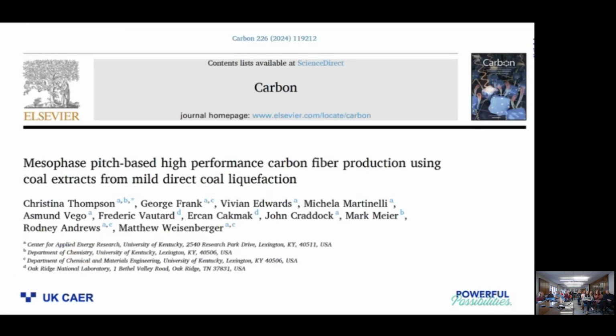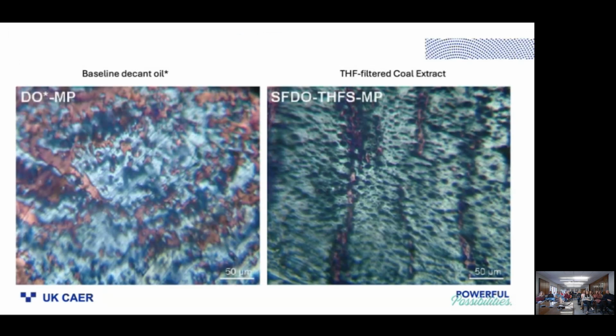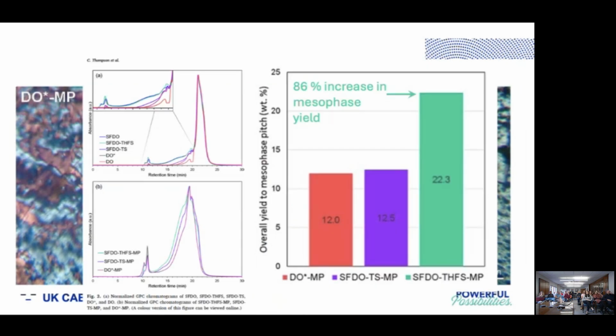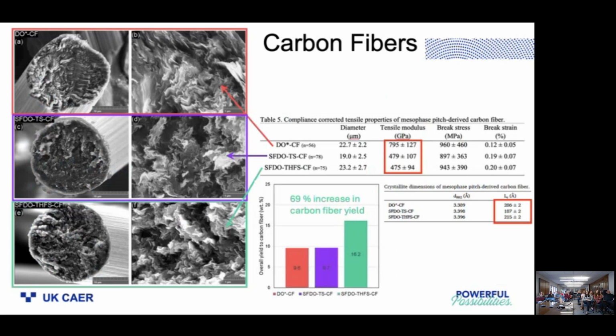We published a paper on having achieved a high performance carbon fiber from coal extract back in May, and I want to get at the takeaway of that. Bottom line, when we used our coal extract relative to our petroleum decant oil, which is the baseline for the study, we were able to produce 86% more mesophase pitch than we otherwise would have. That's a win. And at the end of the day, we produced 69% more mass, more carbon fiber than we otherwise would have. So that suggested we could rationally utilize these coal extracts for the production of carbon fiber.